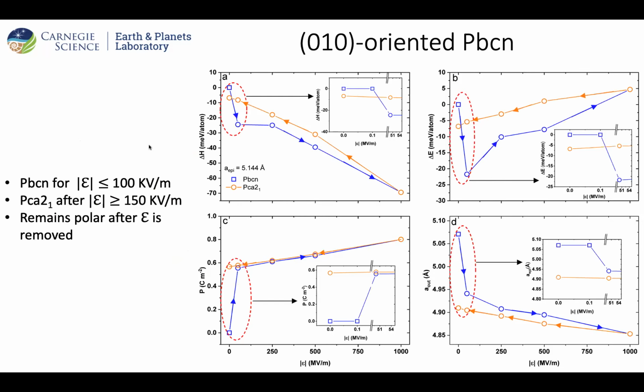Doing so, we plotted the electric enthalpy, the internal energy, the polarization, and the out-of-plane lattice constant. We see a phase transition occurring, driven by the electric field, around 150 kilovolt per meter. So this is kind of an order of magnitude smaller than what is used in a wake-up effect experiment.